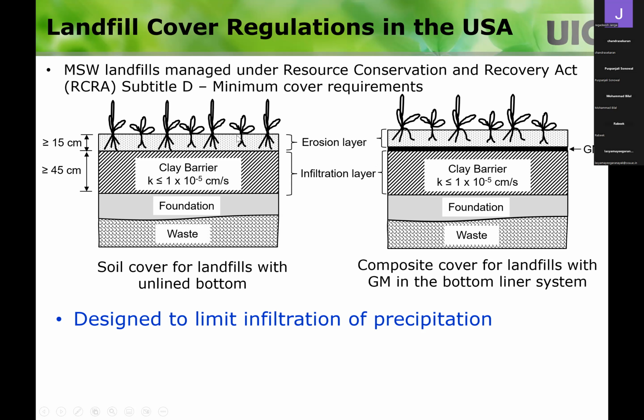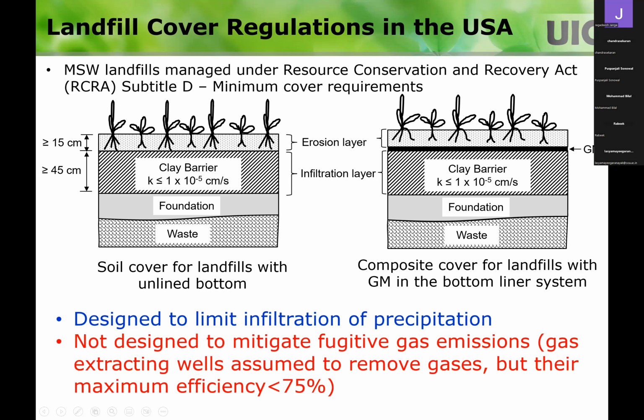So if you have that one, when it rains, you're not allowing the water to get through it. Sometimes you will have a drainage layer between the vegetative, the erosion layer and the infiltration layer to allow any infiltration to drain off sideways. So the whole idea of this cover is not to allow any water to get through it. However, in developing these minimum requirements, they didn't consider the fugitive gas emissions. The gases were not considered.